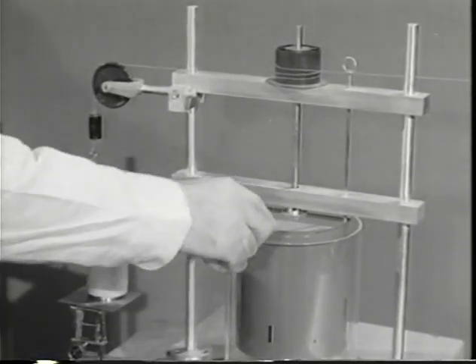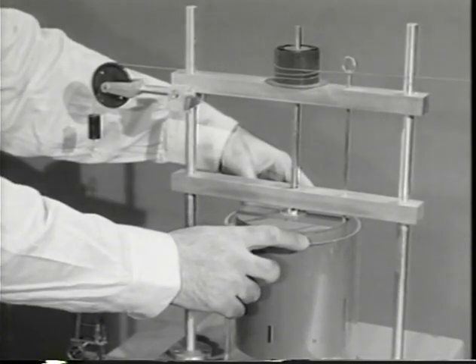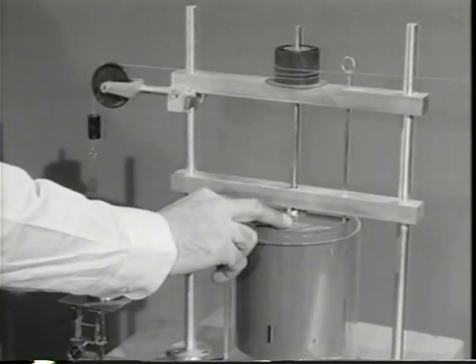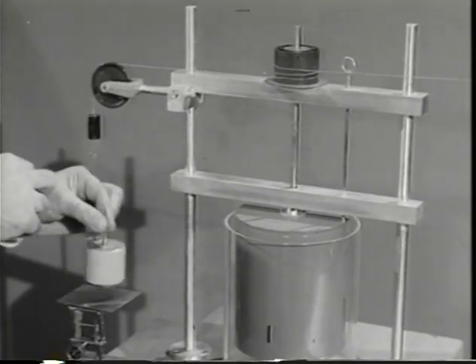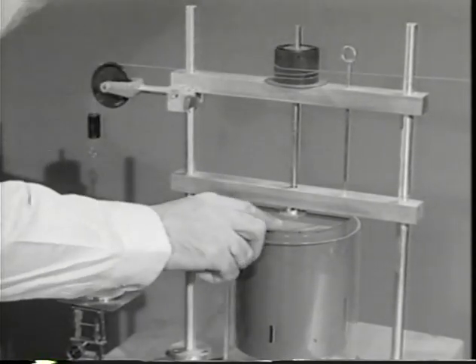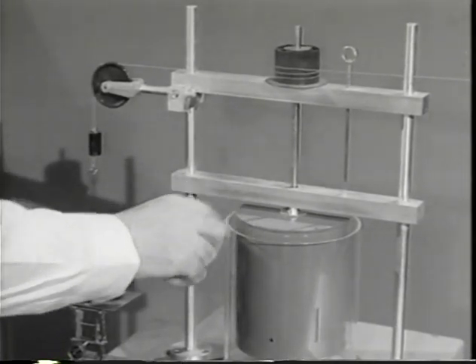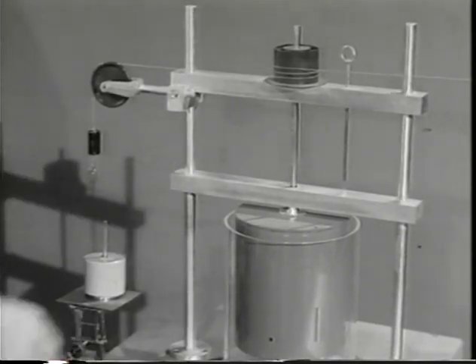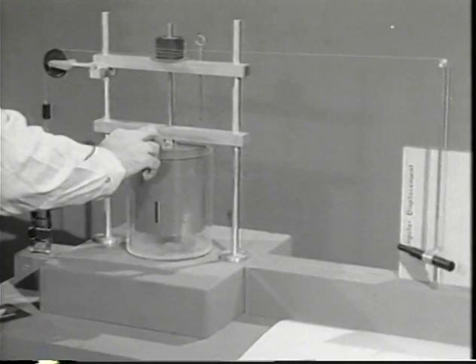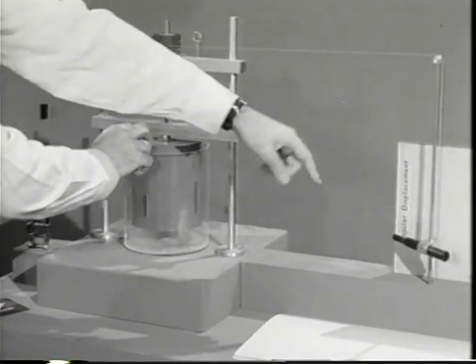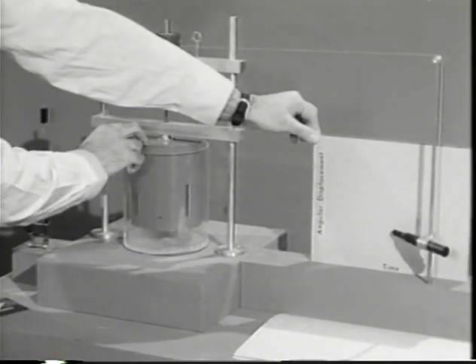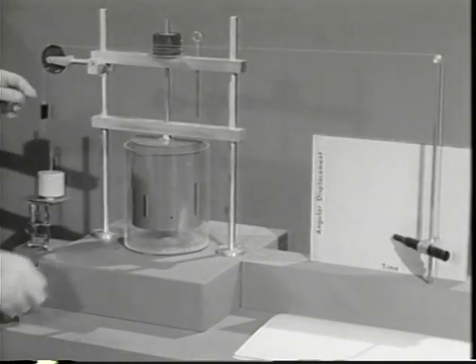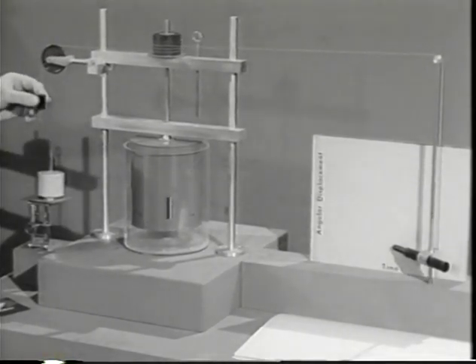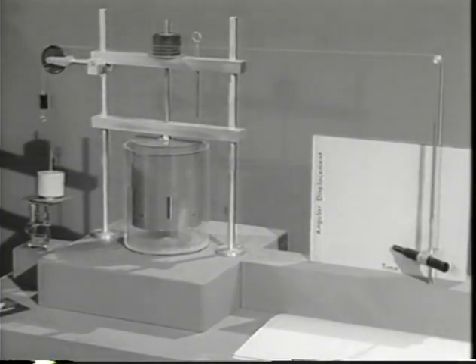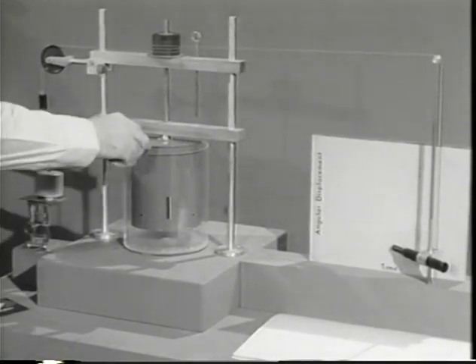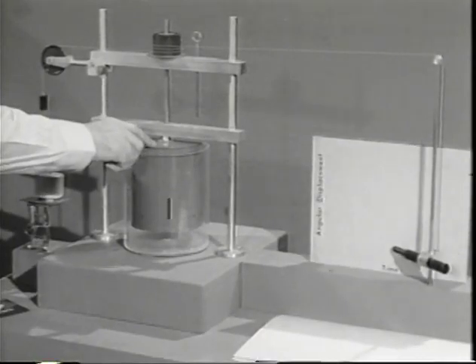The test liquid is confined in this annulus. The outer cylinder is held stationary, and we can apply a torque to the inner one with this weight, which we can hang there. A trigger here releases the mechanism. To remove the torque, there is a slip toggle there. We can record the response of the inner cylinder, that is, its angular rotation as a function of time, with a pen on a chart moving at constant speed. The weight of the recording pen is counterbalanced by this small weight. We have, of course, designed this experiment to minimize extraneous effects arising from the inertia of the fluid, the inertia of the moving parts, and from friction.